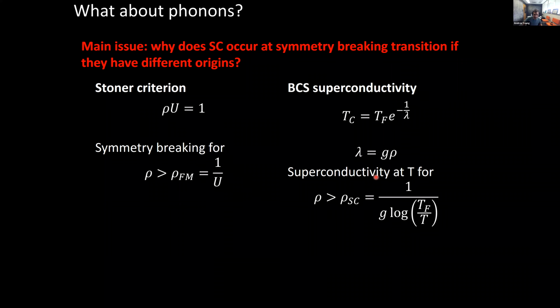Okay, and I think there's actually a relatively elegant synthesis of those two things, which I previewed in the first slide of this talk, which is just the fact that both magnetism and superconductivity happen when the density of states becomes large. Both of them, in a sense, give you some critical density of states above which something interesting happens. We can call one of them rho ferromagnetism and the other rho superconductivity. And even from unrelated mechanisms, it's not unexpected for these things to coincide.